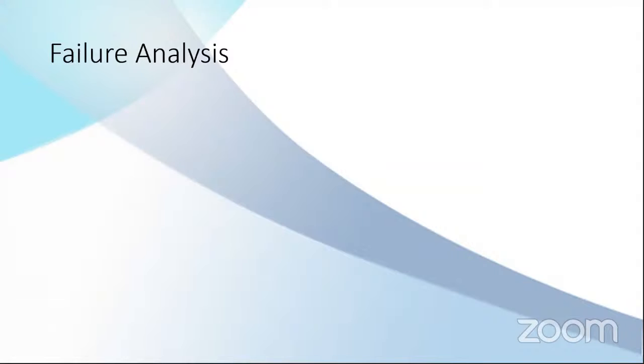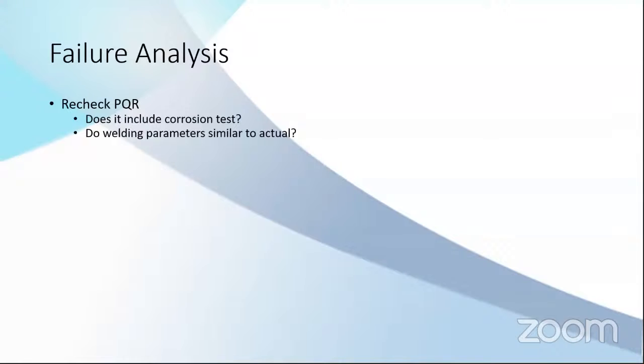This is the one that we don't want to have, failure analysis. When it really happens during service, what I normally do during the failure analysis, first, I check the PQR: does it include a corrosion test, and do the parameters look similar to the actual welding in the field? If it doesn't have a corrosion test, then the PQR is questionable. You need to qualify it again to see if the weld has good corrosion resistance.